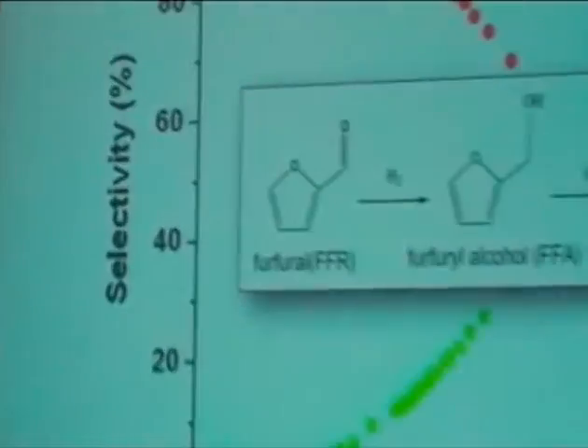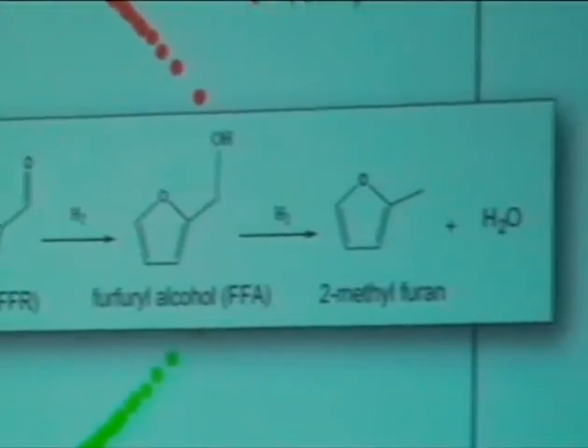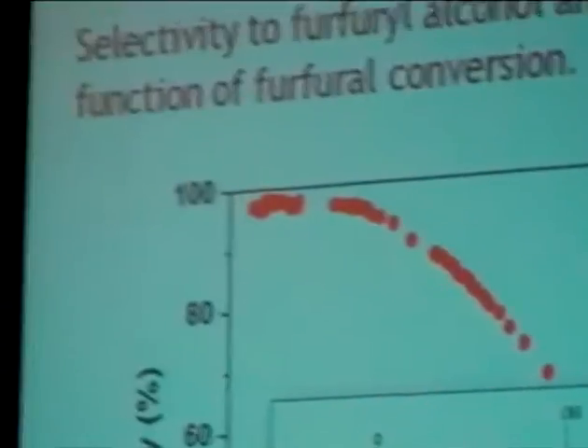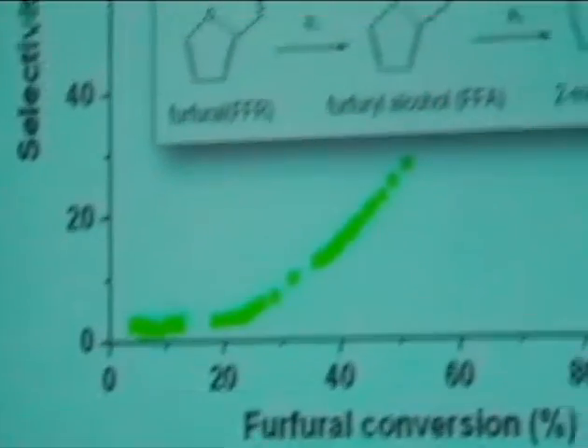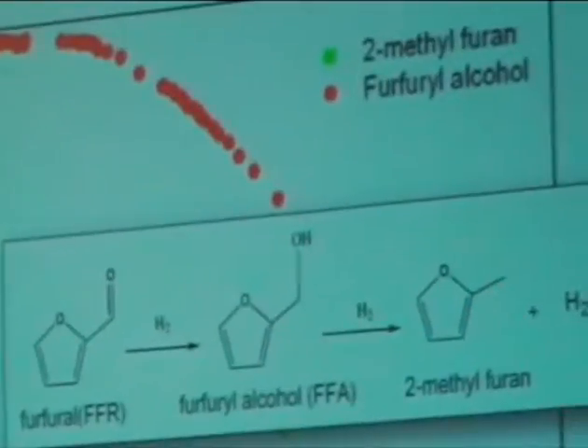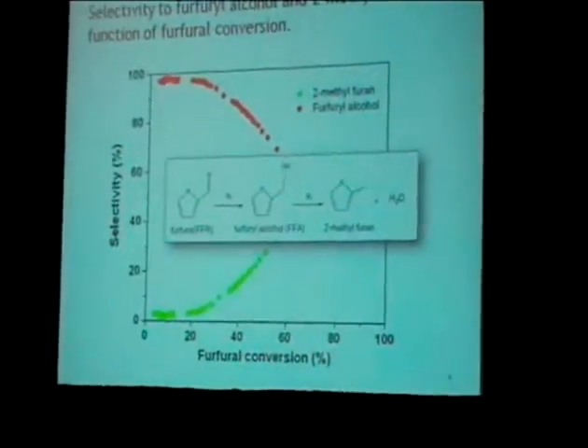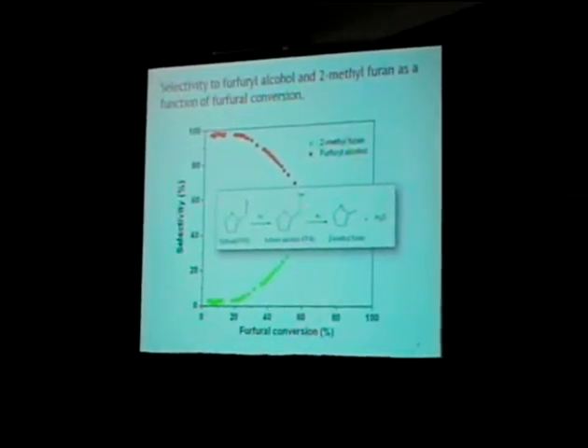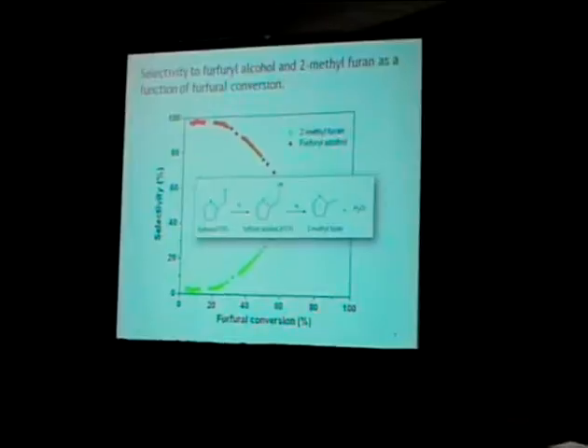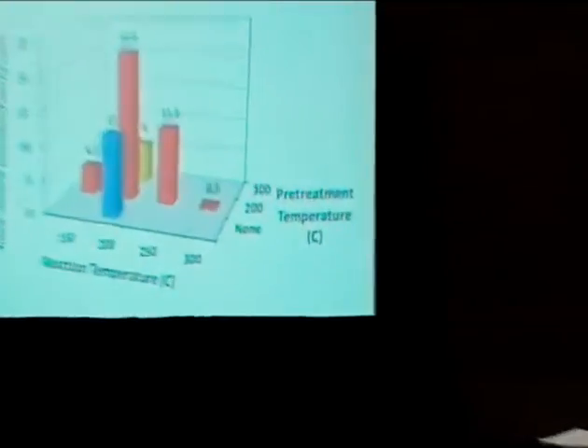In addition, as we increase the furfural conversion here, you can see that the selectivity to furfuryl alcohol, our preferred product, goes down. At the same time, the undesired product, which uses up too much hydrogen, 2-methylfuran, goes up here. So there's a problem here with overhydrogenation, and we're very interested in seeing if we can cut down on this step as opposed to the step here, which eventually will give us the levulinic acid that we're interested in.